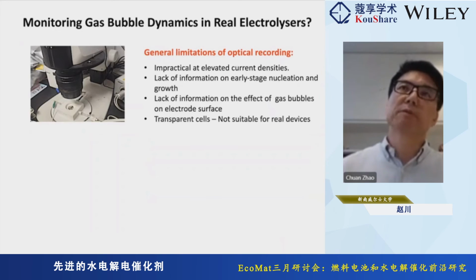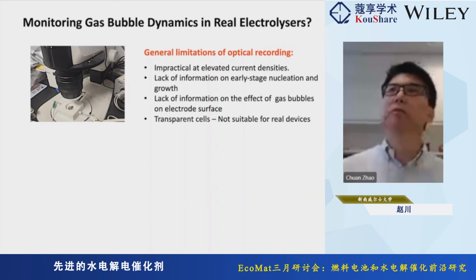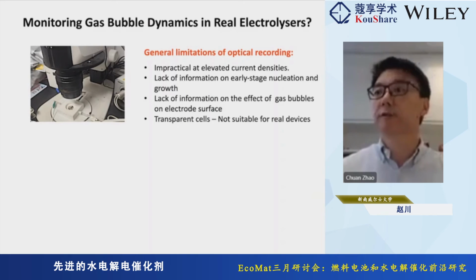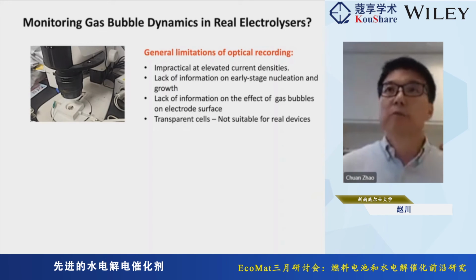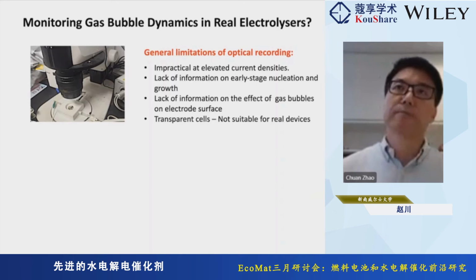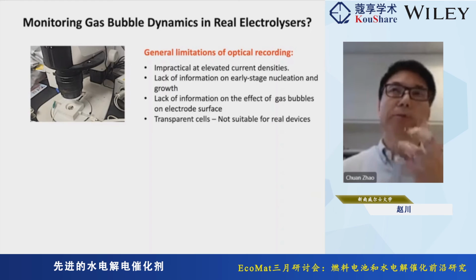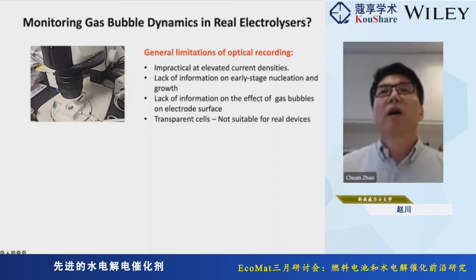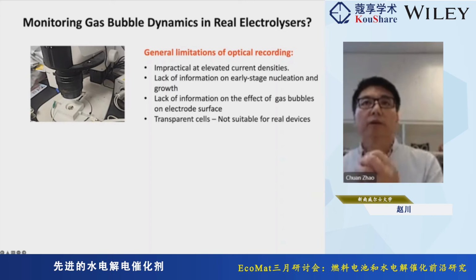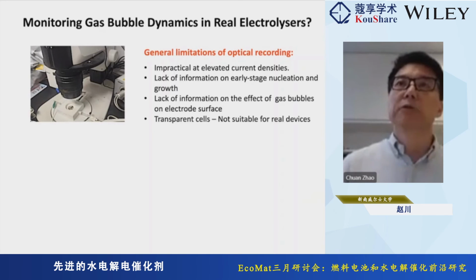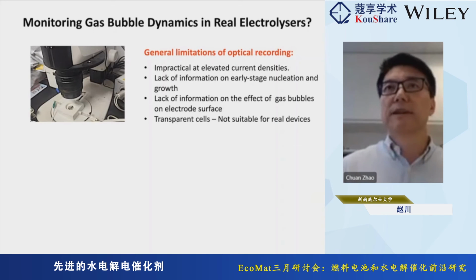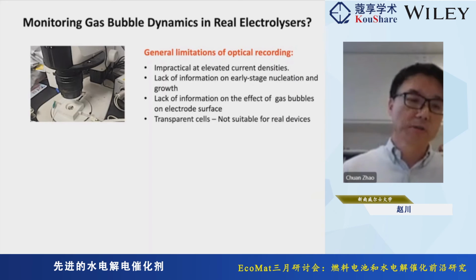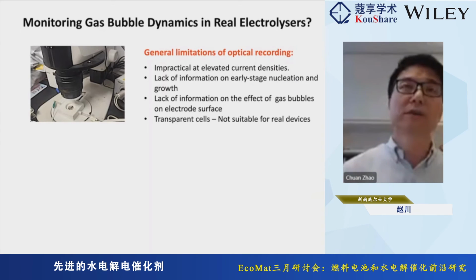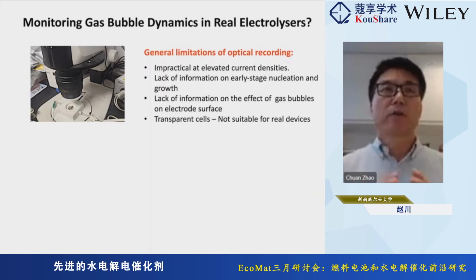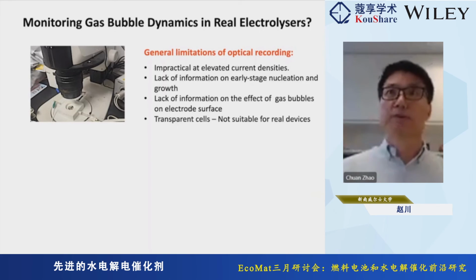But we noticed one problem with optical recording, which is probably the only available method to really monitor this gas behavior. There are lots of limitations. For example, we can't really see much at high current density, where the bubble evolution is very strong. And there's also a lack of information on early stage nucleation and growth, because due to the resolution of the microscope, you can only see a bubble once it grows to a certain size.